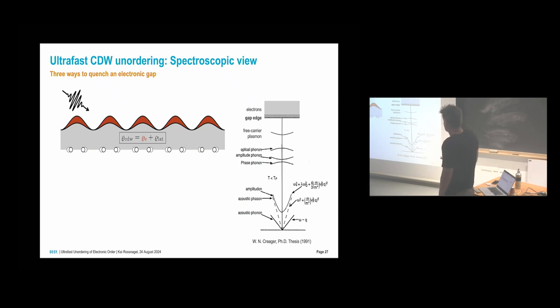This will be a major point. And then if you look at the processes and the excitations involved in the destruction of such a state, you find a lot of excitations inside your gap. You find the phonons, the acoustic and optical phonons. You find the excitations of the charge density wave, the amplitude mode, amplitudon, and the phason, and you find other types of modes, amplitude phonons, phase phonons that couple to the gap. You maybe find free carrier plasmons. So there's a lot of excitations going on inside the gap, and all of this you will probably excite when you hit your sample with this optical pulse.